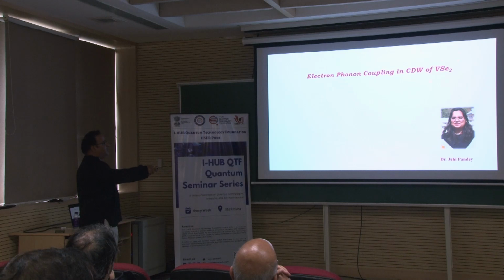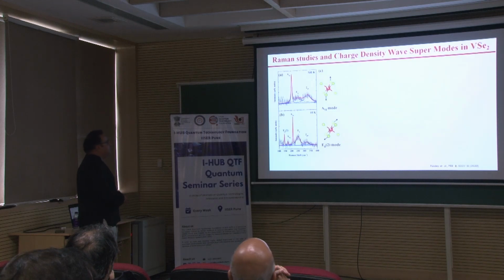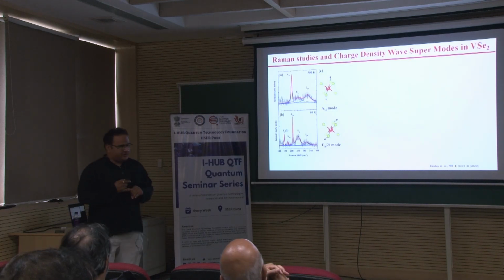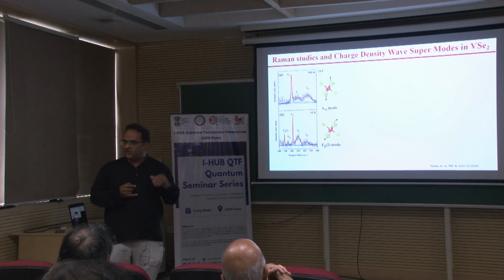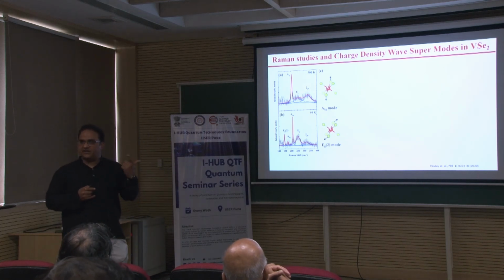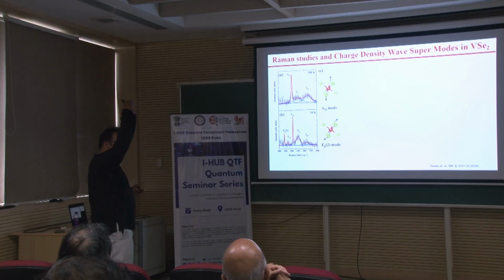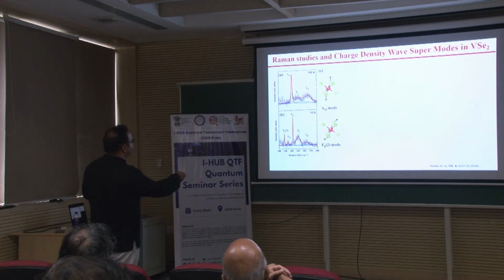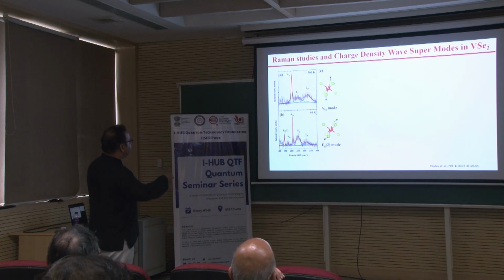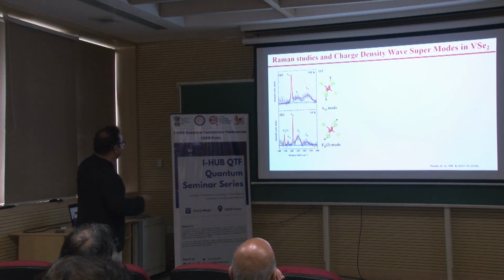We started actually in 2019 with one of the PhD students. She was working on 1T VSe2. If you look at the transition metal dichalcogenides and do the Raman spectra, you usually get the A mode and E mode. The A mode represents the out of plane vibrations, the E mode represents the in plane vibrations of the atoms. For example, this is the Ag mode, where the vibration of the chalcogen atom is out of plane, and here it is the in plane mode.